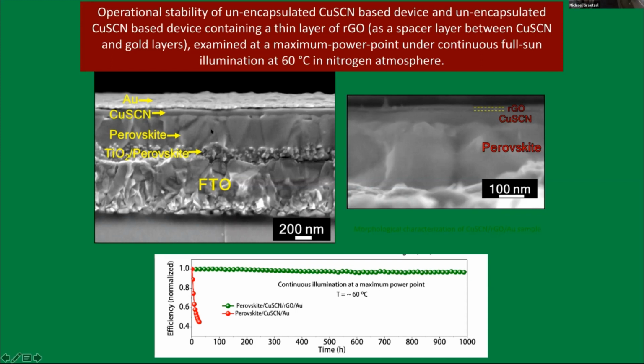They're not there yet, but this thing is moving forward, and a lot of people are working on it. I mentioned to you the 15,000 papers. And so here you see that structure, the perovskite, copper thiocyanate, and that made all the difference in the world. And why was that? Well, under light, you create a voltage across the cell at maximum power point. And under this, that voltage created a deterioration of the back contact between copper thiocyanate and gold. And that caused the degradation. It had nothing to do with the perovskite.